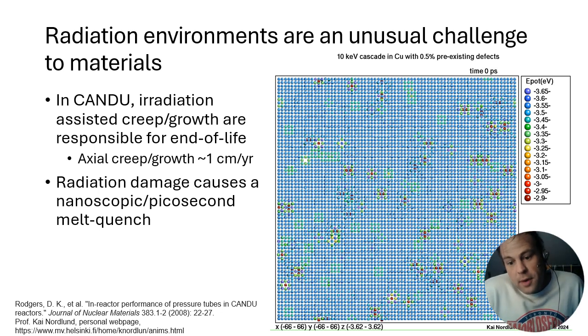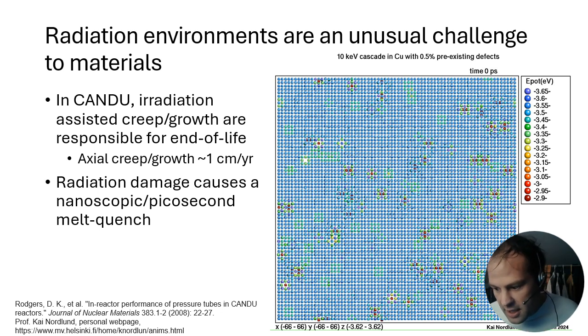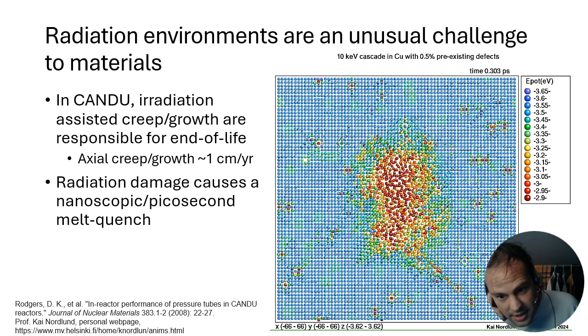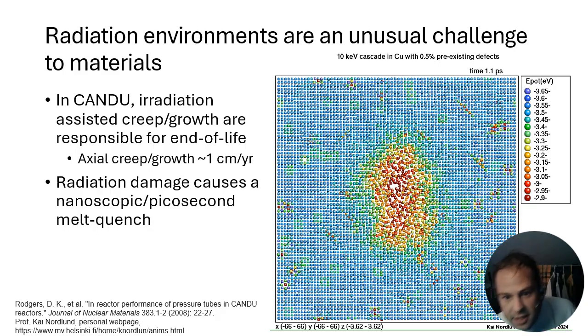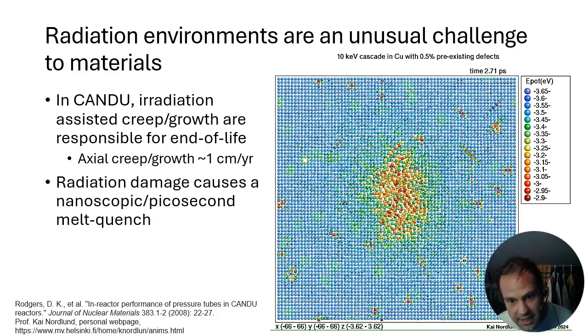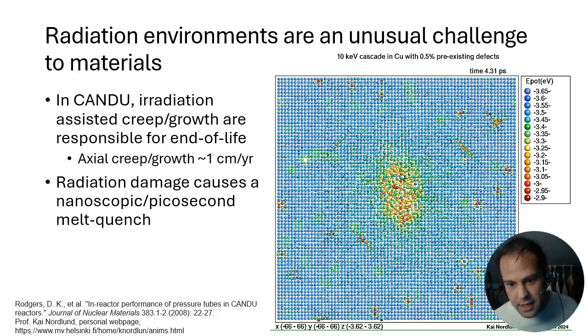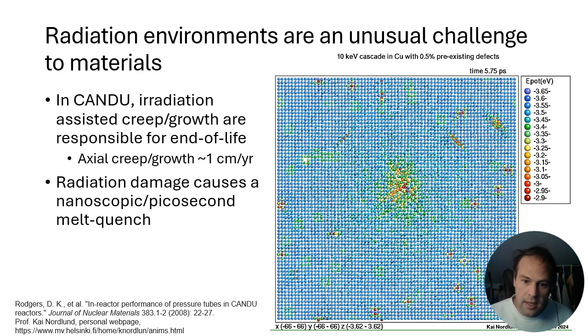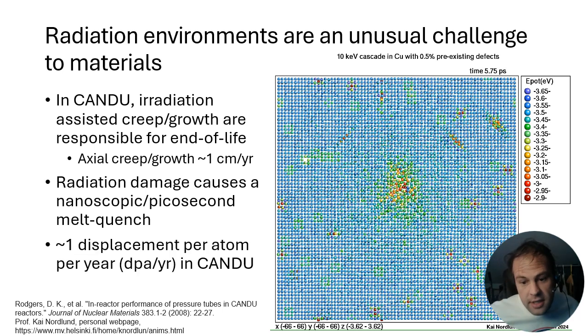The reason that these tubes grow by 1 centimeter per year is that radiation damage is a process by which massive energetic particles interact with atoms in a material lattice and impart some kinetic energy to an atom in a lattice and knock an atom out of place, pushing it into an interstitial site and leaving behind a vacancy. Here's a little picture from Professor Kai Nordlund's research, in which a single particle is given a high amount of kinetic energy. This results in a very fast, over the span of a couple of picoseconds, a melt, and over the next tens of picoseconds, a quench. In CANDU reactors, we have dose on the order of 1 displacement per atom per year.